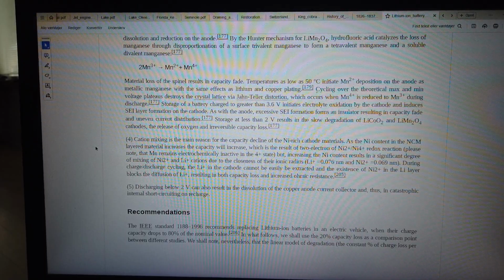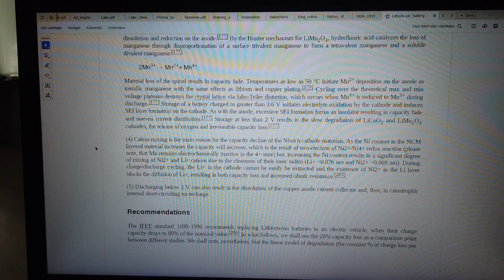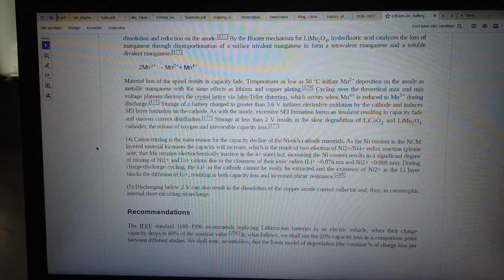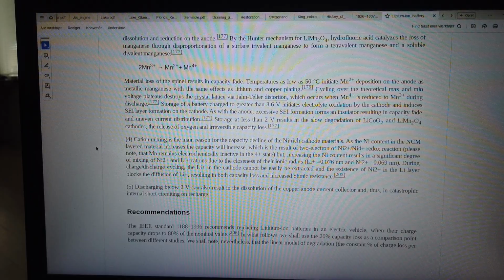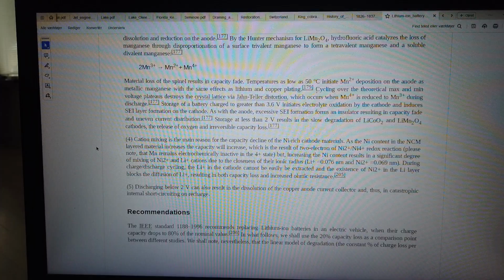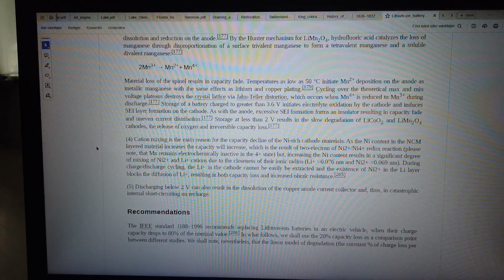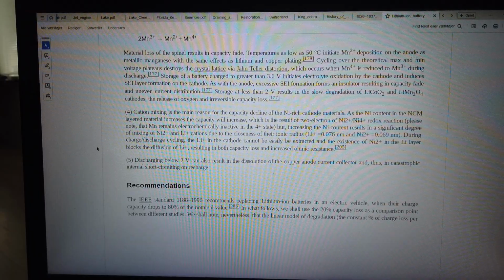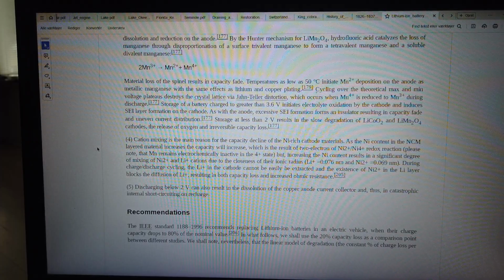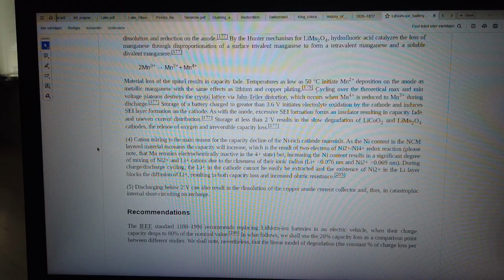Li+ equals 0.076 nm and Ni2+ equals 0.069 nm. During charge/discharge cycling, the Li in the cathode cannot be easily extracted, and the existence of Ni2+ in the Li layer blocks the diffusion of Li+, resulting in both capacity loss and increased ohmic resistance. 5. Discharging below 2 V can also result in the dissolution of the copper anode current collector and, thus, in catastrophic short-circuiting on recharge.